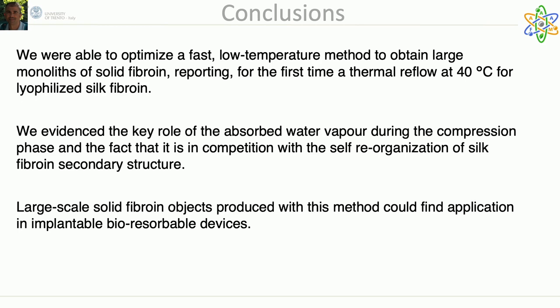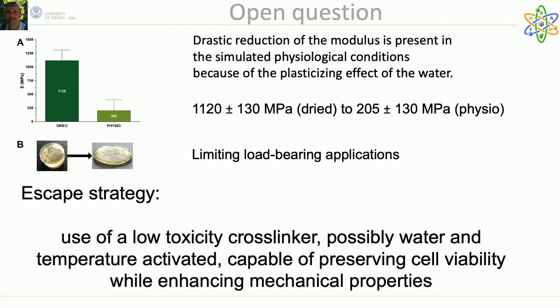We could evidence the key role of the absorbed water vapor during the compression phase and the fact that it is in competition with the self-reorganization of silk fibroin secondary structure. We strongly believe that large-scale solid fibroin objects produced with this method can find application in implantable bioresorbable devices, particularly when one issue still present in the obtained material is resolved.